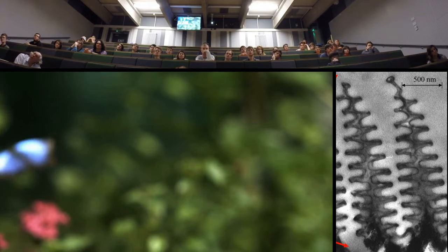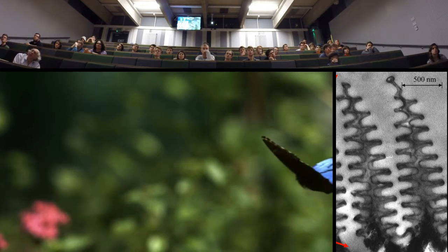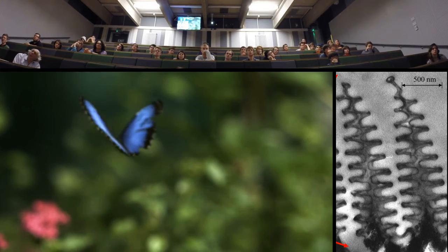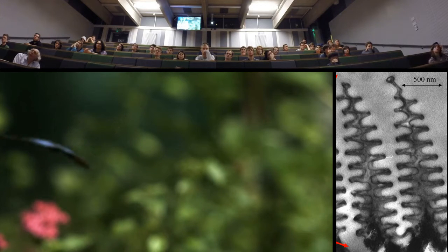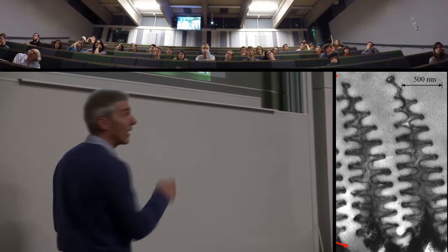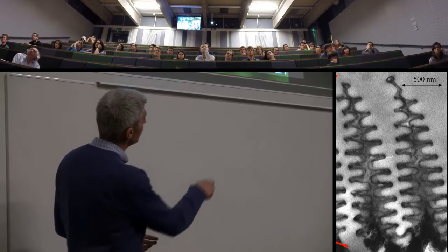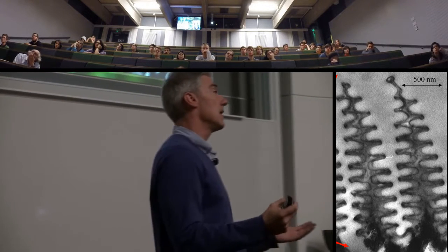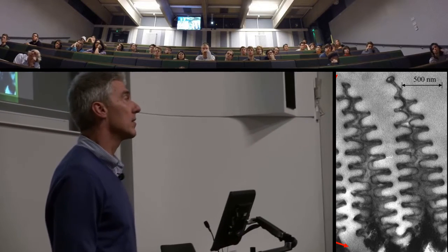The coherent scattering, that's another phrase for it. As we look down on that, we're looking down on this. So these are the tops that we see just here. And it's those layers, in fact, it's the thickness of these layers and their refractive index and the gaps between them that have evolved perfectly to give a bright blue reflection. If we were to change these layers, thicknesses, or their material, then we would affect the color reflected.